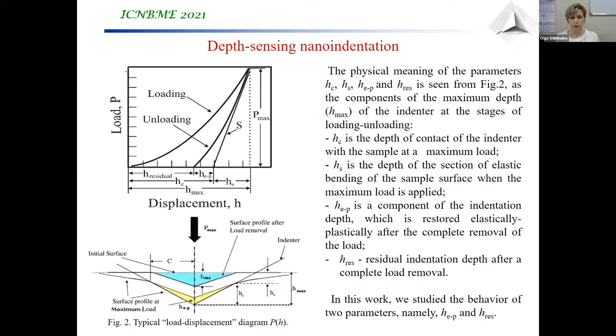The nano-indentation process includes the main stages of loading and unloading. During loading, the deformation of material takes place, and during unloading, the relaxation of accumulated stresses with the relaxation of indentation depth takes place. From this parameter of indentation depth, we can characterize the elastic-plastic relaxation of the material. In this work, we studied the elastic-plastic relaxation of the indentation and the residual depths of indentation.